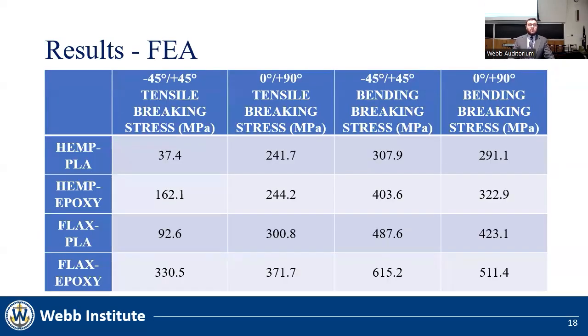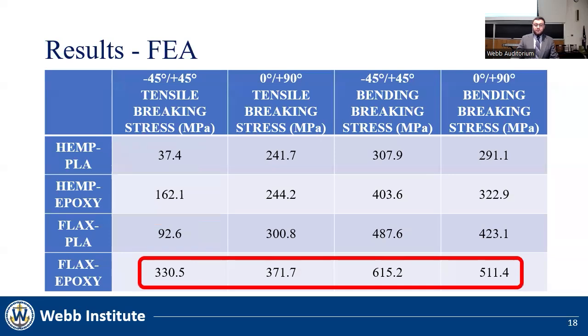Displayed here are all the results from the FEA testing. It is important to notice the very low tensile breaking stresses when the strength of the PLA matrix is put under the most stress in the 45-degree fiber orientation. The strength of the flax epoxy composite is the highest for each test, so I will be utilizing only this composite for physical testing.